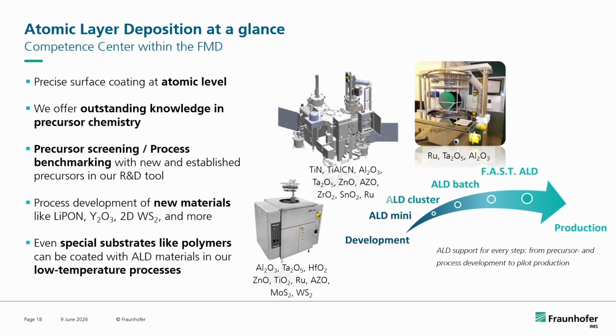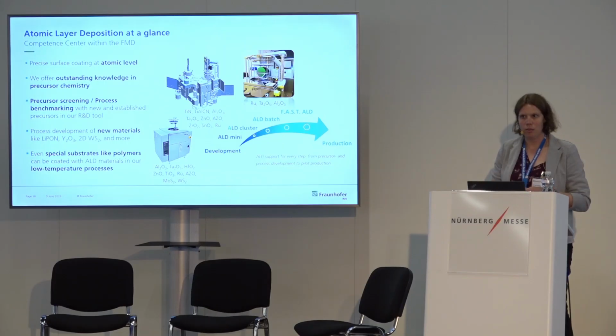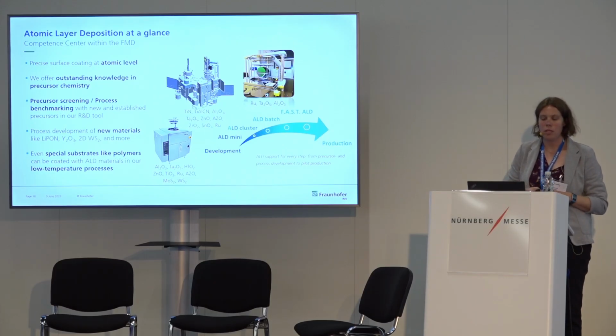If the throughput needs to increase more, then we can also use our batch system. Here we have the possibility to coat up to 25 wafers at the same time, which is, of course, a great advantage concerning the time, because ALD is a very slow process. Just to give you an idea, for 50 nanometers of aluminum oxide, we would need around 3 hours. So if you want to process 25 wafers, then you would need 25 times 3 hours, so it's a time-consuming process. But here we have the chance for some standard materials and also for ruthenium to decrease the time by depositing it in just one step.